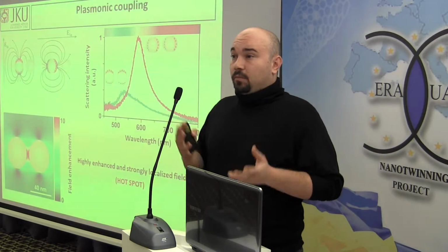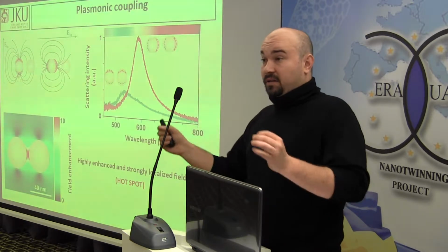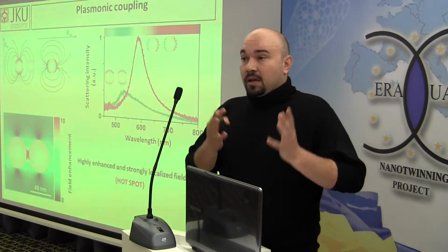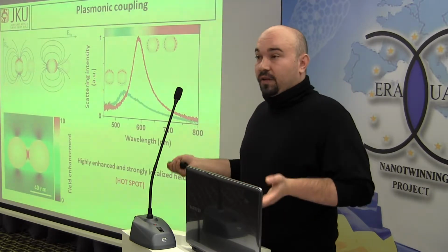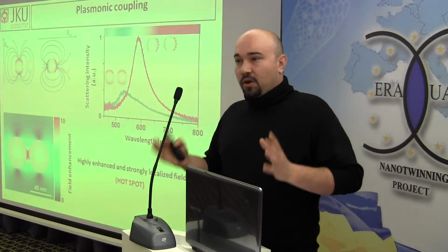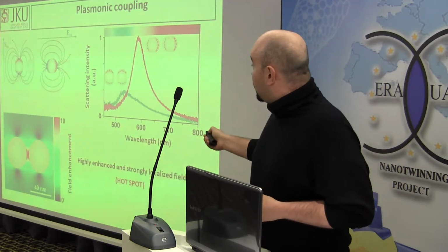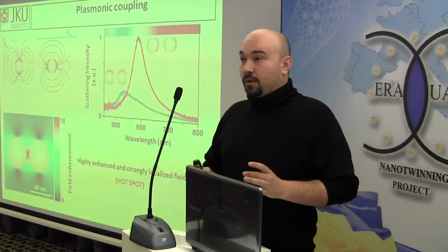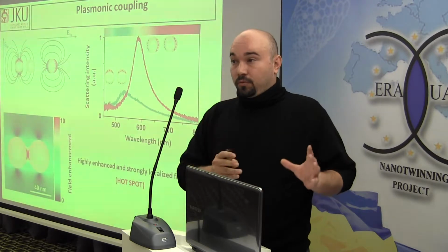Plasmon modes, one can treat them like coupled dipoles in the first order. So when two nanoparticles are close together, the plasmon modes can couple. Now the optical properties depend on the excitation polarization, and one gets two different plasmon modes, the transversal one and the longitudinal one. For most applications, the longitudinal plasmon mode is more important, since we have an increased scattering cross-section. The resonance redshifts and all the optical properties of the longitudinal plasmon mode are distance dependent. It's so-called the plasmon ruler.